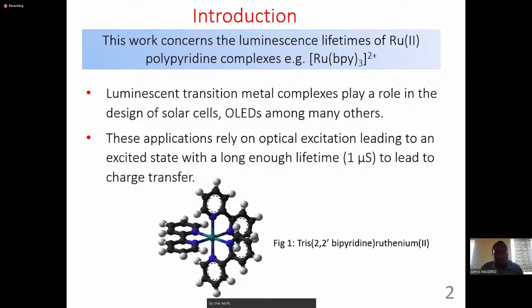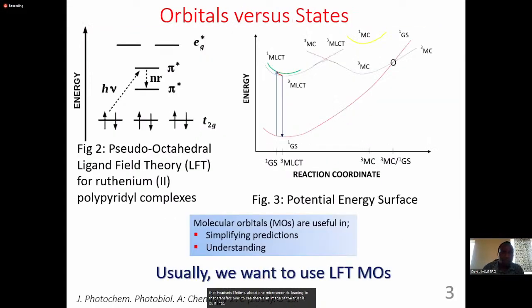This work concerns the luminescence lifetime of ruthenium polypyridine complexes such as ruthenium tris-bipyridine. We're interested in this problem because transition metals play a very important role in the design of solar cells, organic light emitting diodes, among many other applications. The basic idea is that there's an optical excitation leading to an excited state, and you require a long excited state lifetime of about 1 microsecond, leading to charge transfers. What you see there is an image of tris-bipyridine ruthenium-2.